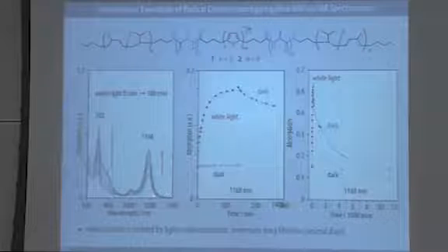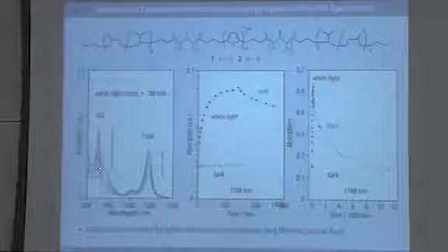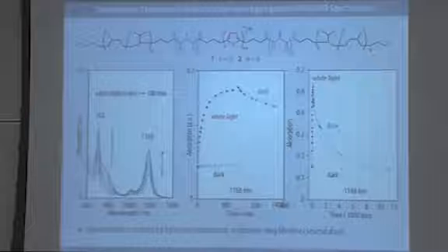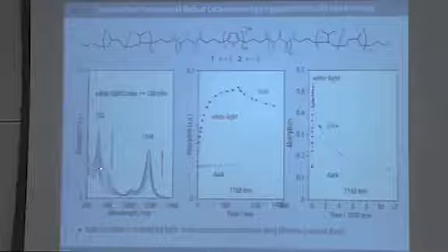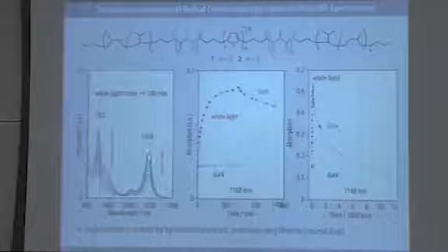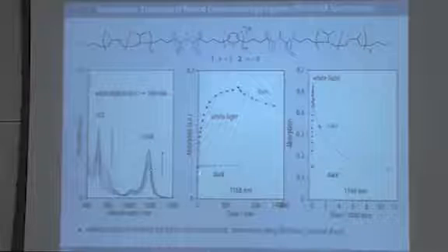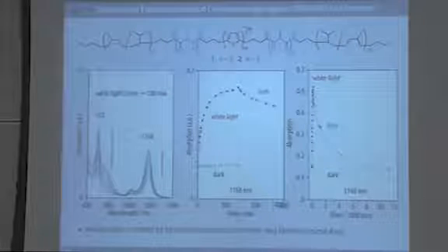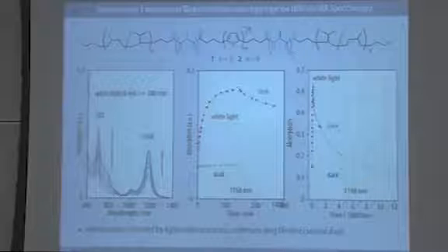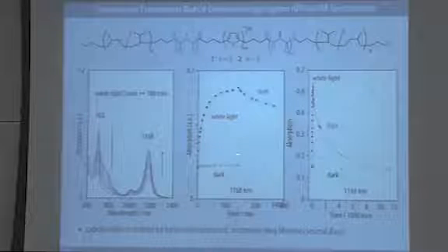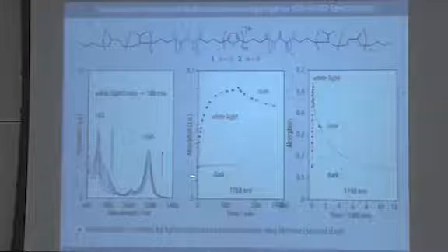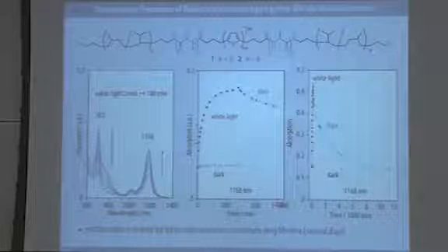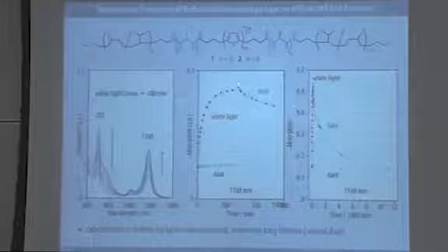So if you take a solution that has just been cooled so that the nanofibrils form, but not given a lot of time yet, and you expose it to white light, then you see that these peaks drastically increase in intensity, whereas they increase much, much slower if you keep it in the dark as well as possible. As you then switch off the white light,